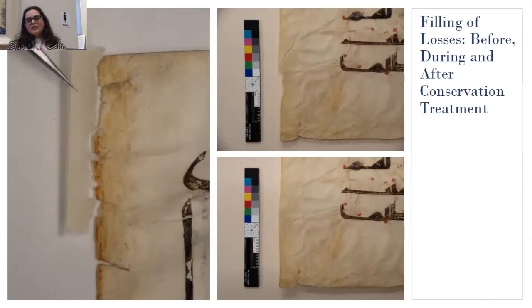So this project is regarding the mending material. But during our study, we noticed that nanocellulose can be useful also for its texture, not only for its strength properties. For example, in this case, we decided to add a layer of nanocellulose as the last layer of an infill, because this type of film has a very opaque and transparent, and in some cases a little bit shiny appearance, as the parchment support sometimes presents, especially on the hair side.